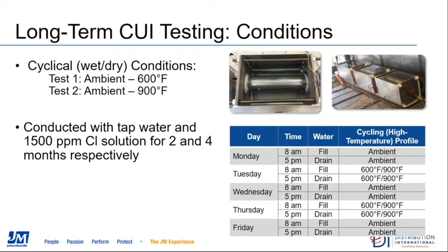So what we see on the chart just below that is the schedule. Again, we are alternating between filling and draining, ambient and process temperature. This is to basically go through as many wet and dry cycles as we can over that 6-month time. So for 2 of those 6 months, the vats were filled and drained with regular tap water. And for 4 of those months, it was a 1,500 part per million chloride solution. Again, a very corrosive solution, trying to look at what's going to happen when pipes are subjected to this punishing test.